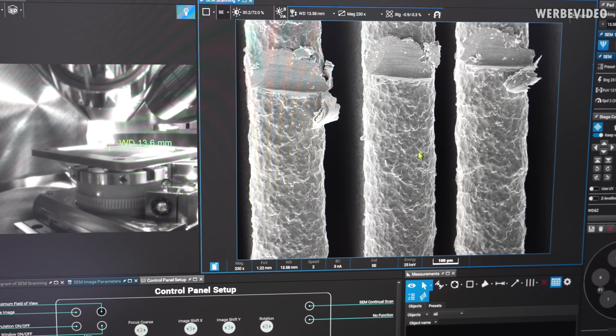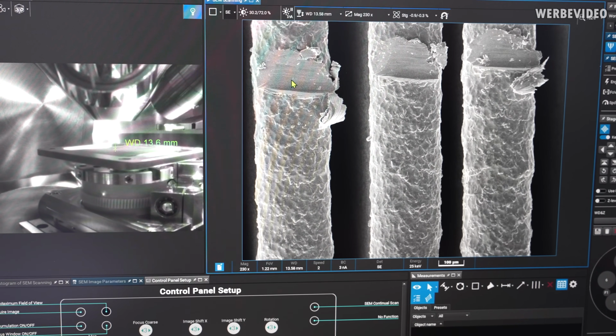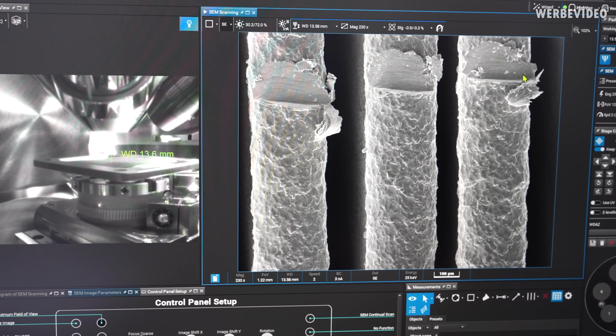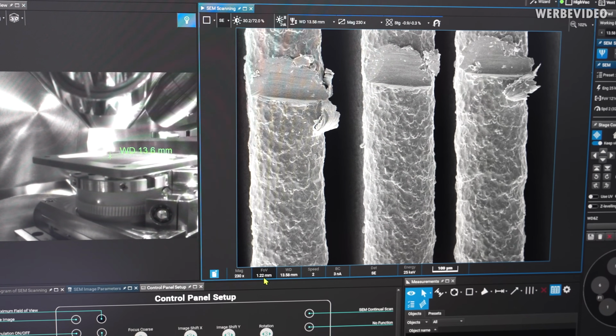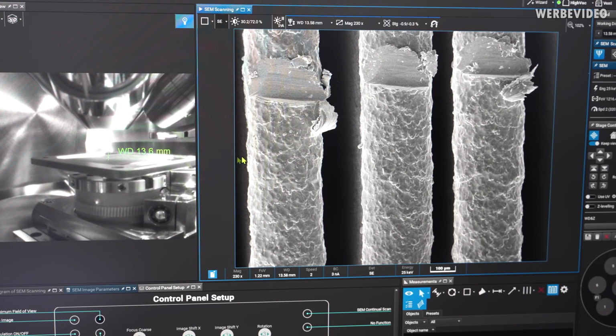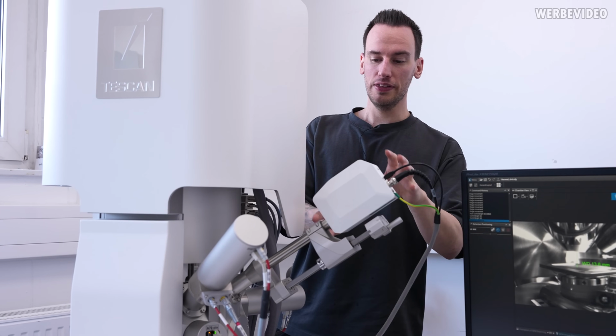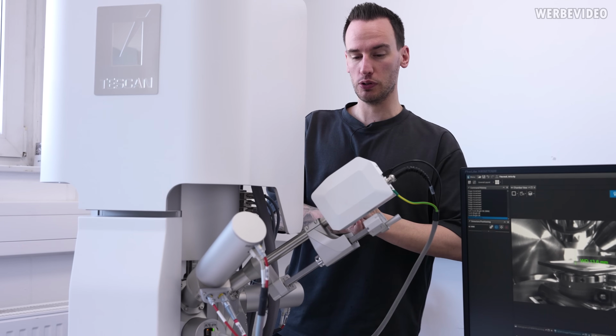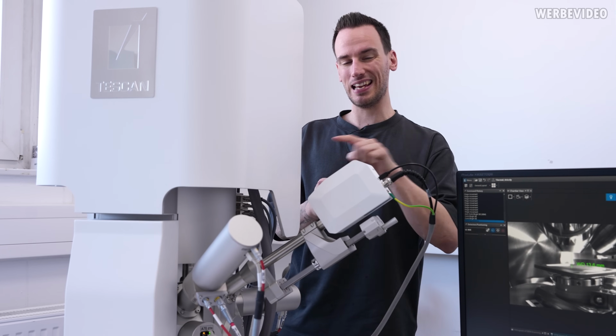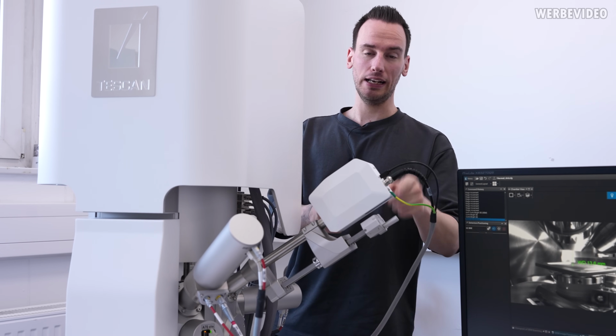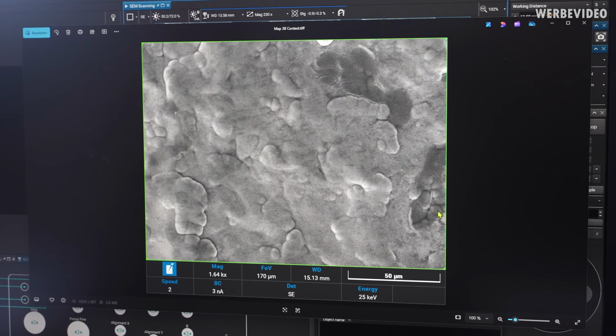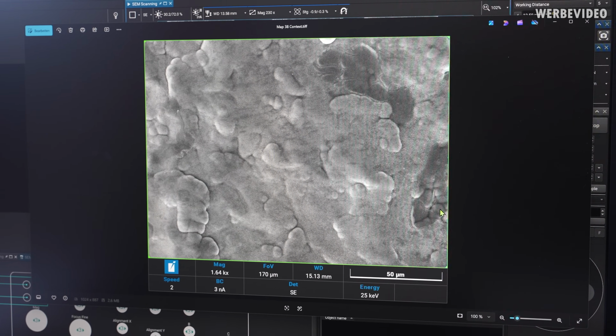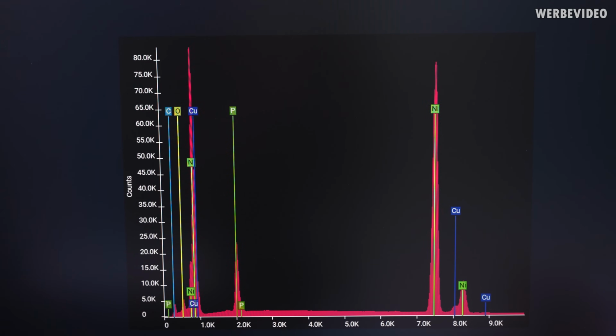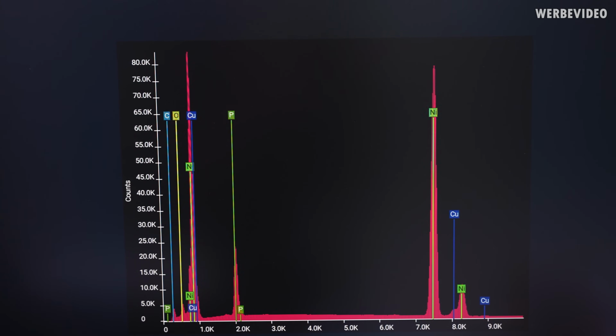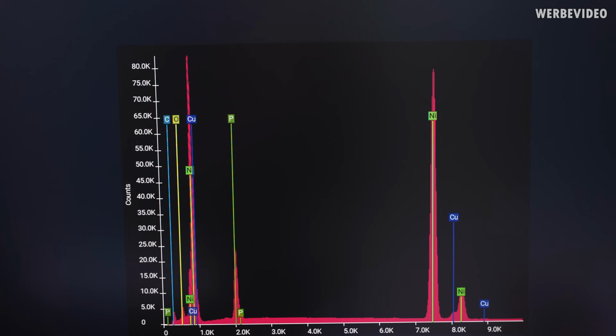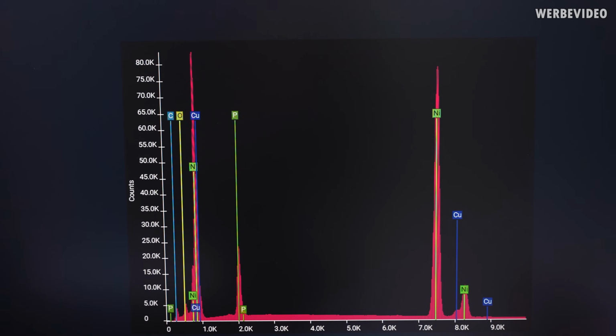What we can see here is the nickel plating. Here, definitely the scratch, how we removed some of the material. And currently the field of view is 1.2 millimeters. So that is the entire field of view from left to right, what you can see. This is the EDX material analysis unit I was talking about. And whenever the electron beam is scanning across the surface, this will be able to tell us which material we are looking at. And if we now zoom into this surface area and try to analyze this, then we're getting this spectrum. And you can see that there is a detection of nickel, of copper, of oxygen, a little bit of phosphorus, which is part of the nickel plating.